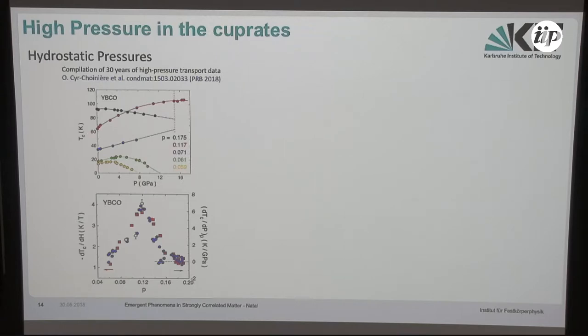At the doping where we are, this is the red curve here, you get a fairly decent increase, I mean from 65K up to 100K at 10 GPa of the critical temperature. So this is a very big increase. So this doping is very sensitive to pressure. And funnily enough, this was noticed by the group of Louis Taillefer: the dTc/dP almost corresponds to the dTc/dH, except that the magnetic field is suppressing superconductivity and the pressure is increasing superconductivity.